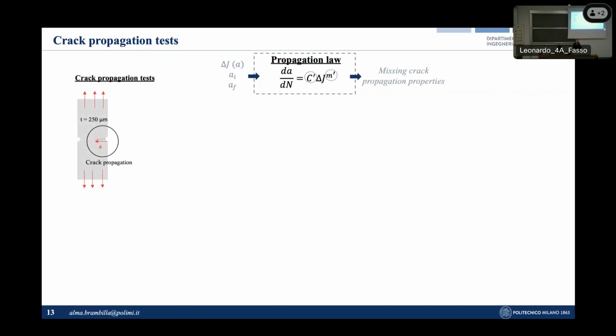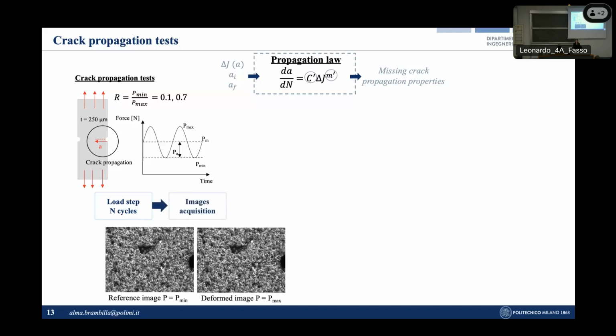So to collect this information, crack propagation tests were performed on notched samples having the same thickness of the wires, which were machined from a nickel titanium sheet. So the tests were performed by applying several load sequences with cyclic load at 2 different load ratios, 0.1 and 0.7. At the end of each loading step, 2 images were acquired. One reference image in correspondence of the minimum load of the cycle, and one image in the deformed configuration with the open crack in correspondence of the maximum load of a cycle.